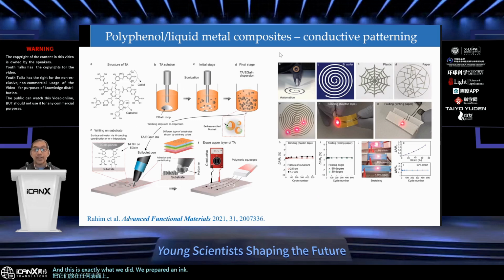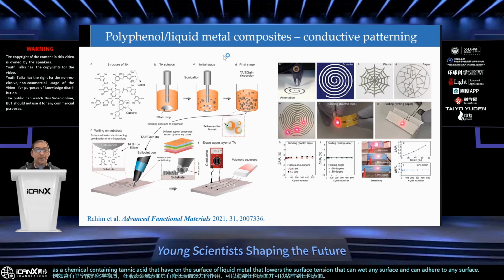We prepared an ink using liquid metal and tannic acid, and we were able to write with a ball pen, which you can see on the bottom left-hand side. If I remember correctly, we were able to write on 28 different substrates. That's quite a huge range, and that comes from the surface active agent, catechol-containing tannic acid, on the surface of liquid metal, which lowers the surface tension, can wet any surface and can adhere to any surface. So that was quite a remarkable work.